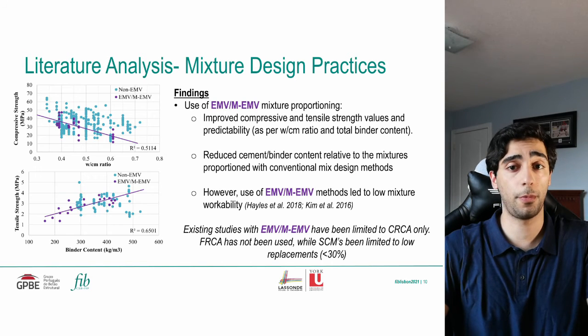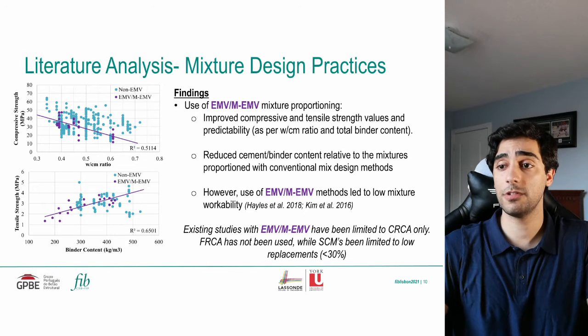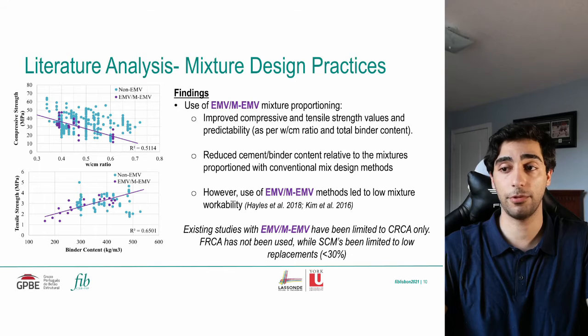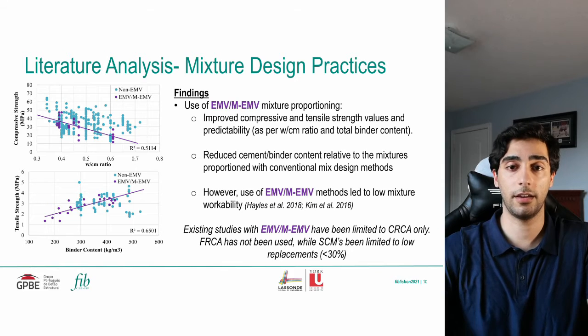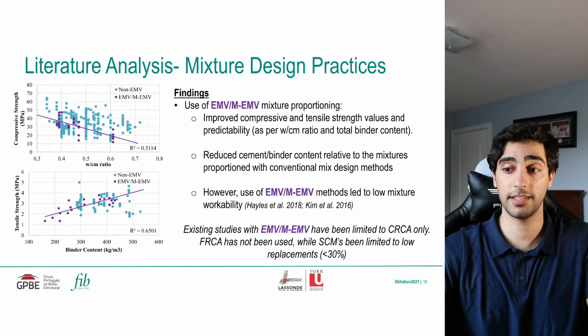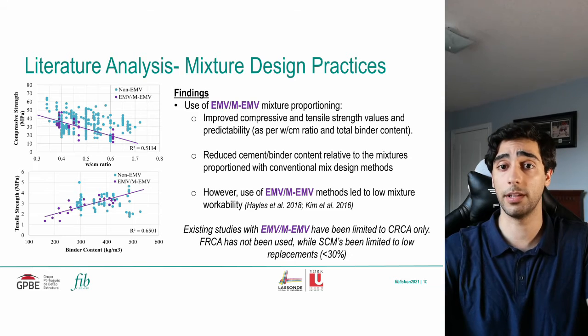In terms of the mixture proportioning methods, it was found that the use of the equivalent mortar volume and modified EMV methods improved the compressive and tensile strength values and predictability as per the water to cement ratio and binder content of these mixtures. It was also found that these EMV-based mixture proportions reduce the cement and binder content relative to the mixture's proportion with the conventional mix design methods. However, it should be noted that these mixtures often display low workability values.